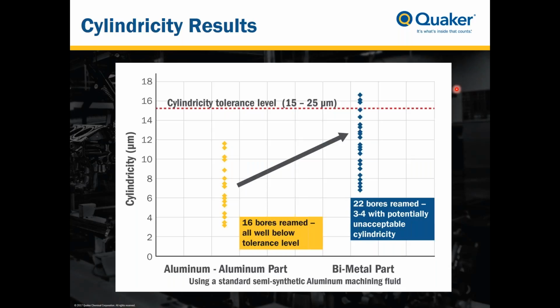Why this is important is, if you look in the literature, you can see some different tolerance levels that people utilize. A real standard is 25 microns. Some are up at 35 microns. Some are even a little bit lower than 25 microns, sometimes down to 15 microns. So if you look at this tolerance level, you can see that if you would ream the aluminum part, you're safe and well below that tolerance level.